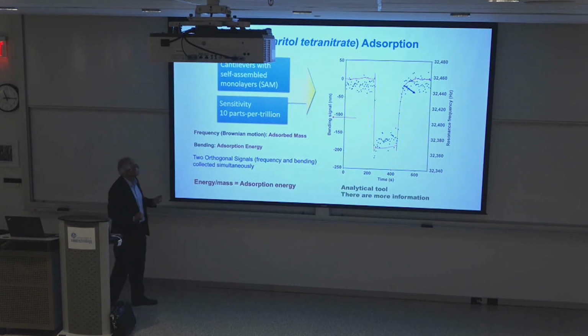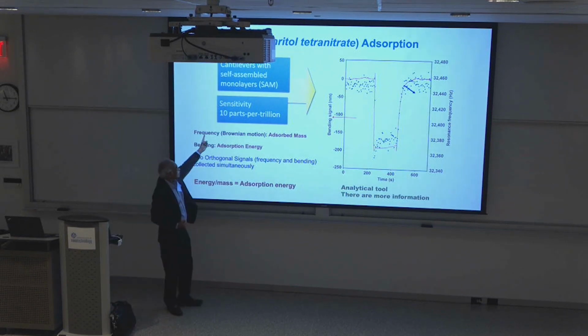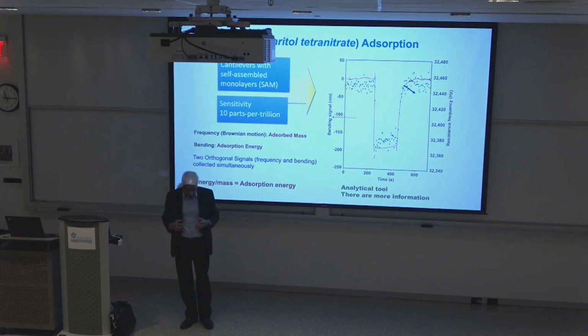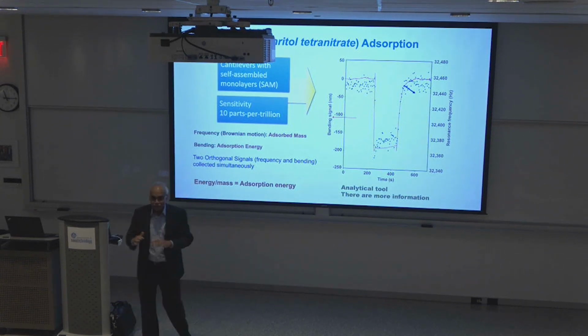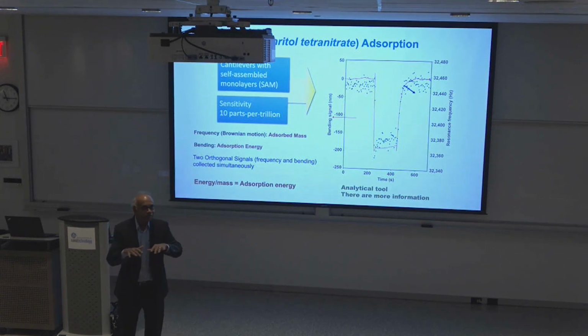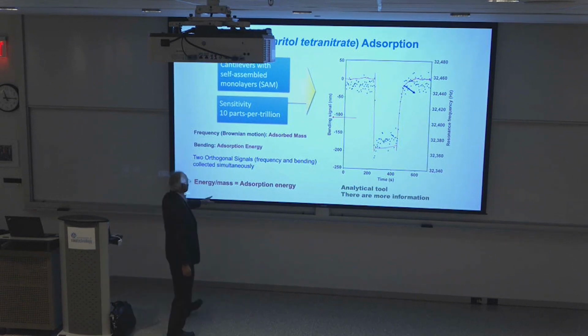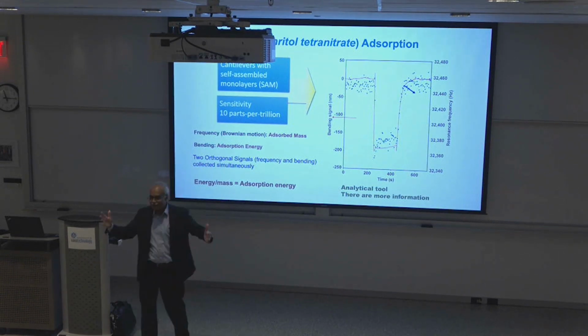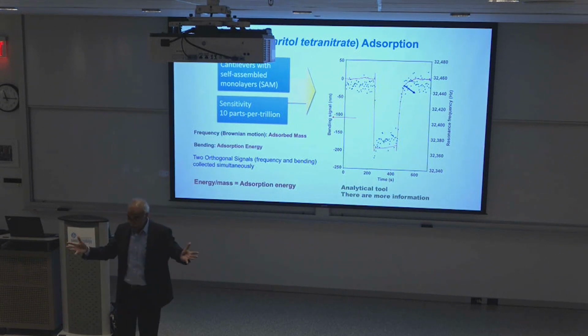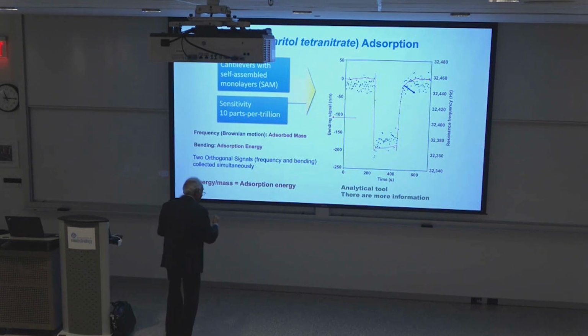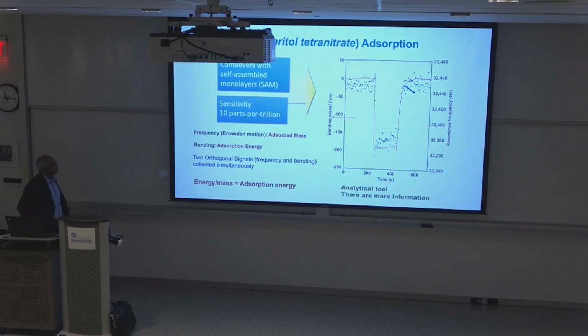So if you do the manipulation a little bit, you can get the absorption energy per molecule, and it comes out to be pretty good. So it is a nice analytical tool actually. How much is the absorption energy per molecule out of this thing? For this material, I think we got 18 kilocal per mole. So that's pretty close. Very simple technique, you can get the real value.